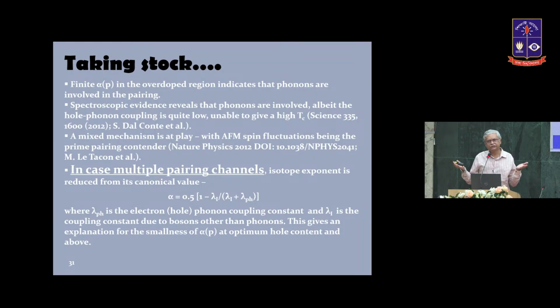So we have a high temperature superconductor, electron pairing must be there. Phonon is playing a minor role. There must be other bosons which are contributing to the superconducting transition temperature. So we call it multiple pairing channel. And there are some indications that spin degrees of freedom, in addition to the lattice degrees of freedom, both contribute to pairing in high TC copper oxides.